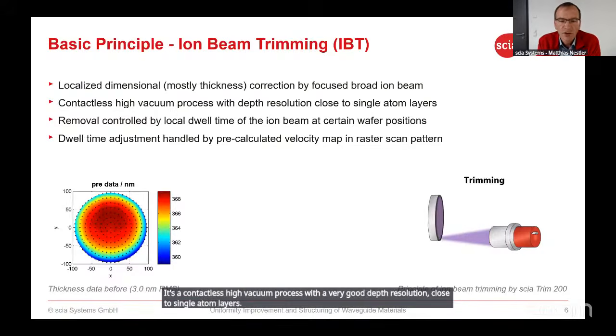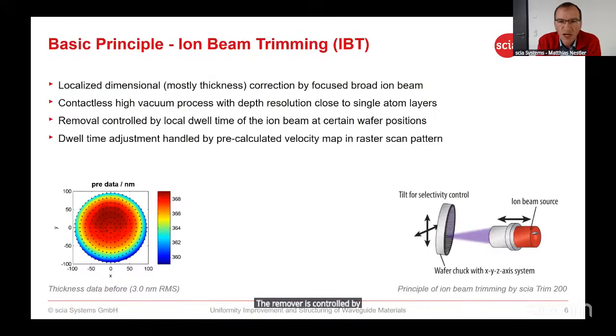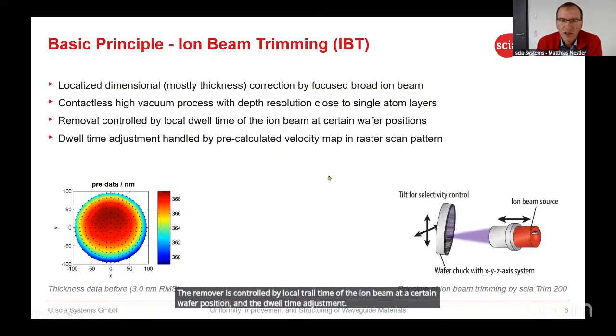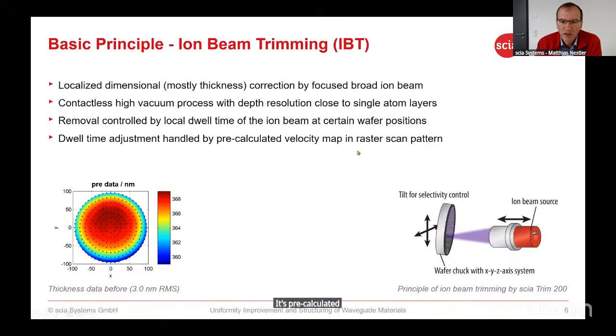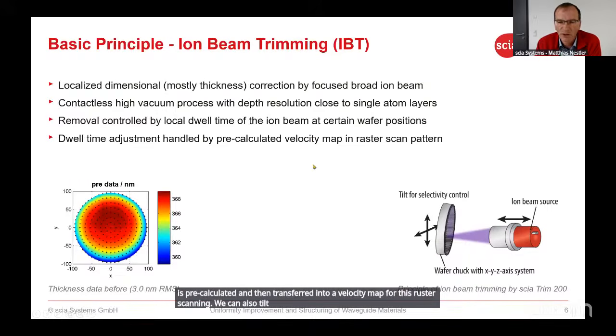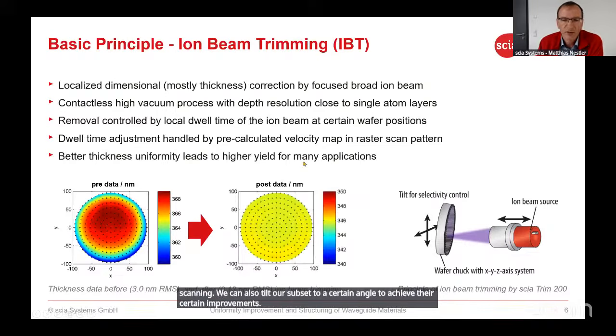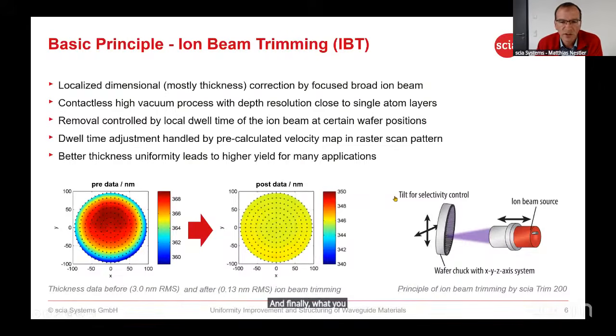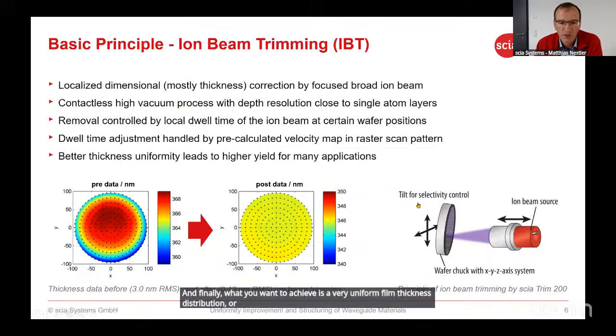The removal is controlled by local dwell time of the ion beam at a certain wafer position, and the dwell time adjustment is pre-calculated and then transferred into a velocity map for this raster scanning. We can also tilt our substrate to a certain angle to achieve certain improvements. And finally, what you want to achieve is a very uniform film thickness distribution or property distribution of your devices, if you have already devices on that.